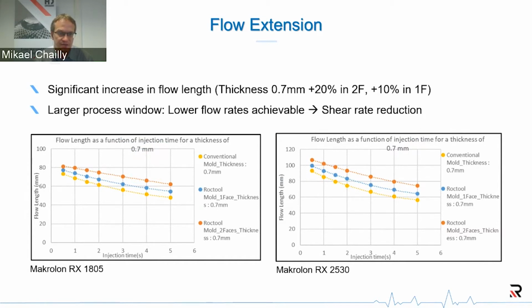In this specific case, about 20%. If we hit only one side with Roctool, the gain is about 10% compared to conventional molding, which is the yellow curve you can observe on both sides. So it means either you could have extended flow length, possibly injecting longer parts with a single gate,